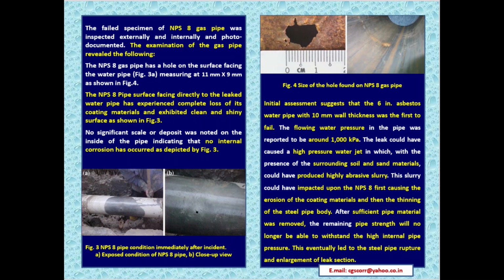The leak could have caused a high pressure water jet which, with the presence of surrounding soil and sand materials, could have produced a highly abrasive slurry. This slurry could have impacted upon the NPS 8, first causing the erosion of the coating material and then the thinning of the steel pipe body. After sufficient pipe material was removed, the remaining pipe strength was no longer able to withstand the high internal pipe pressure. This eventually led to the steel pipe rupture and enlargement of the leak section.